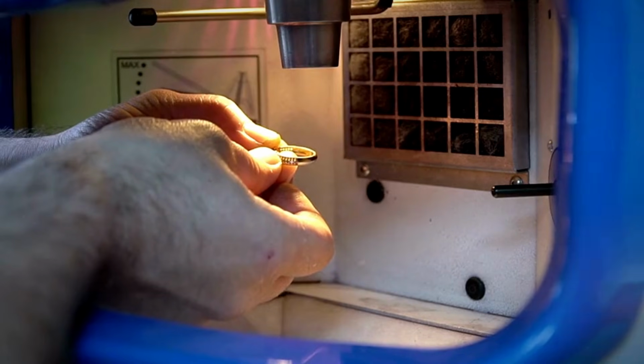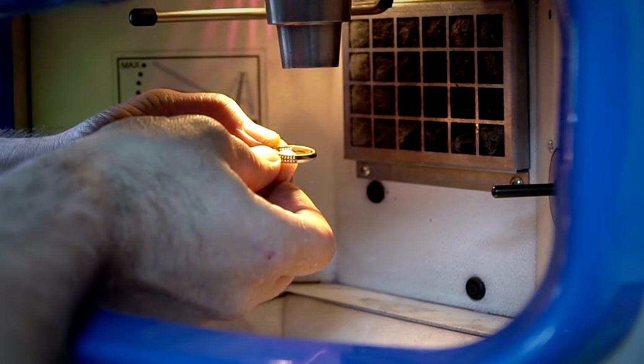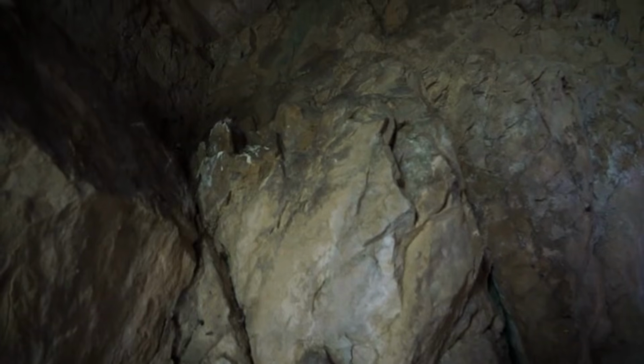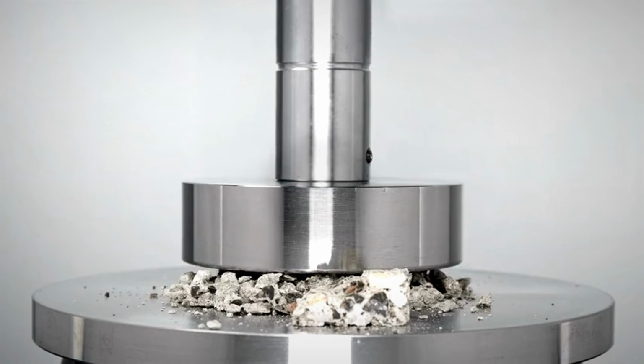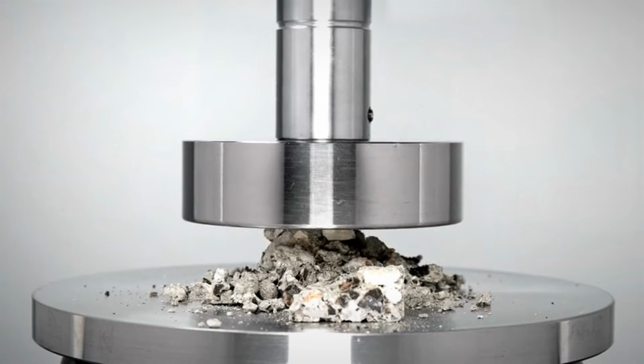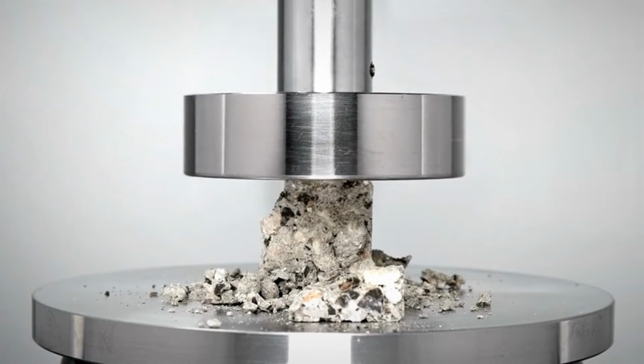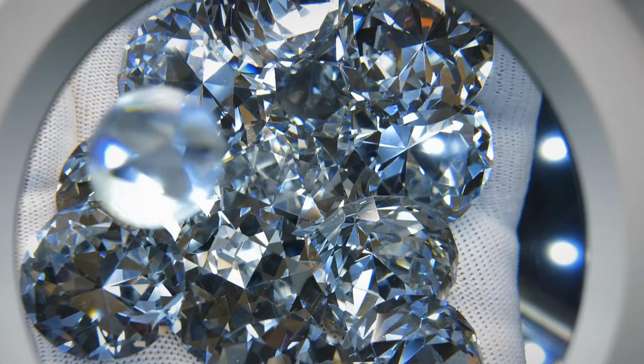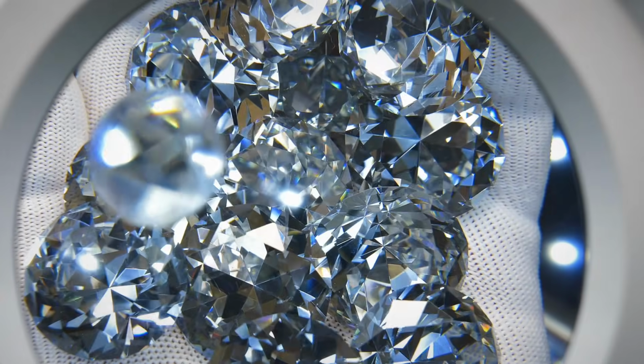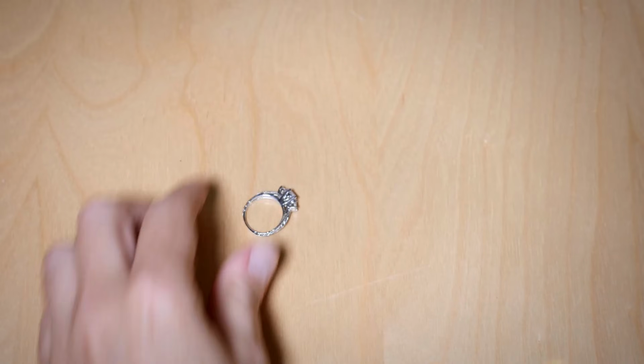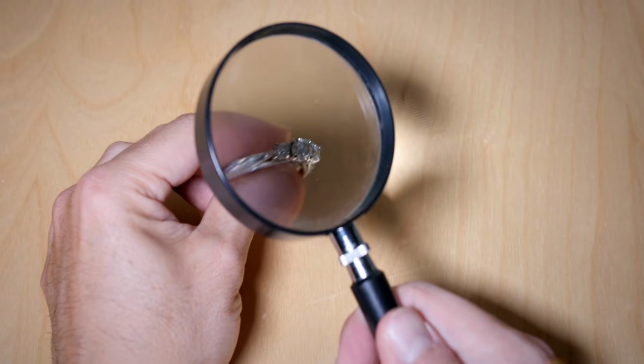To run the test properly, clean the stone first. Residue can trap moisture and obscure results. Perform the test in a dry, room temperature environment, avoiding areas with high humidity. And make sure to compare results with a known control if possible. Even small differences in clearing time can point decisively toward authenticity.